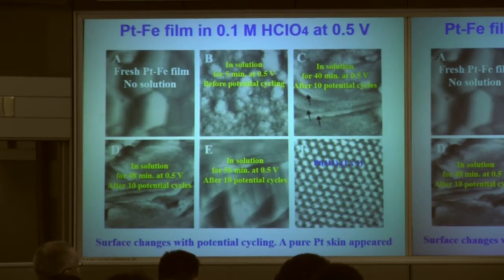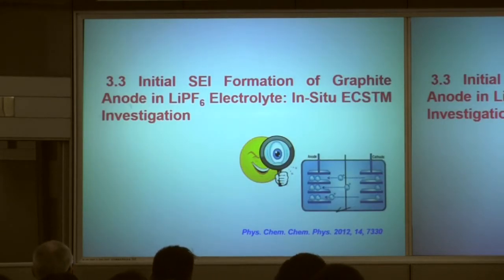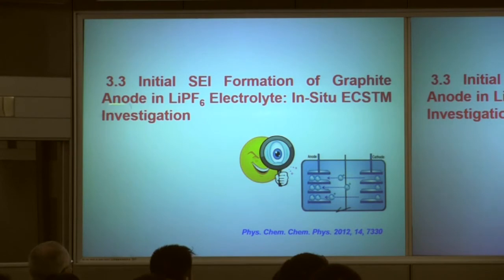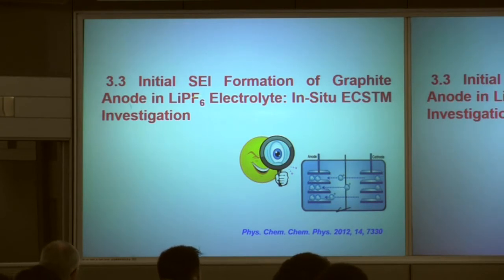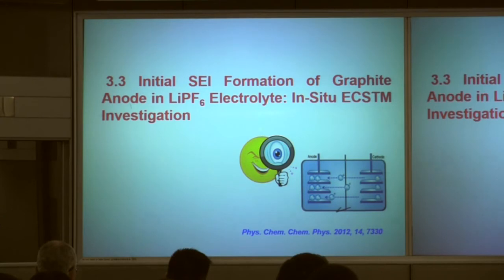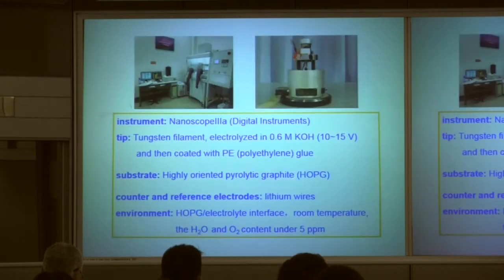This shows that in situ STM is very useful for observing surface processes during electrochemical reactions. We also used this technique to understand SEI formation. For lithium-ion battery study, the SEI (solid electrolyte interface) is very important — its thickness, composition, and morphology all affect battery performance. We did a simple experiment: put graphite in organic solvent and use in situ STM to observe the surface change.